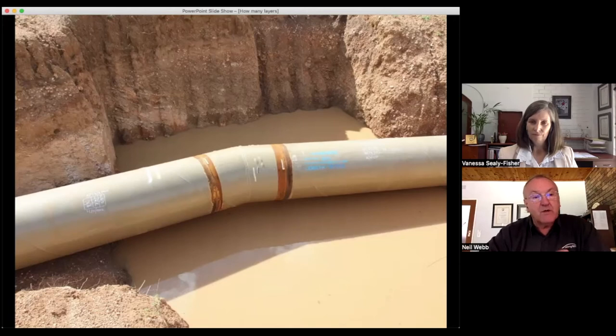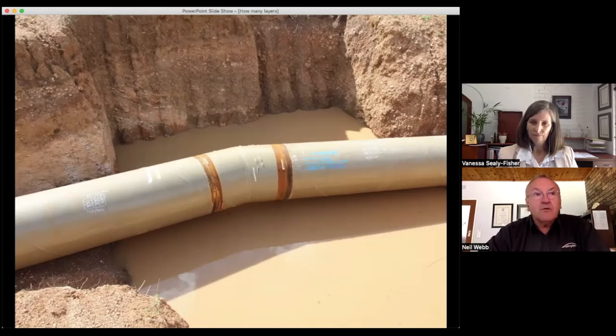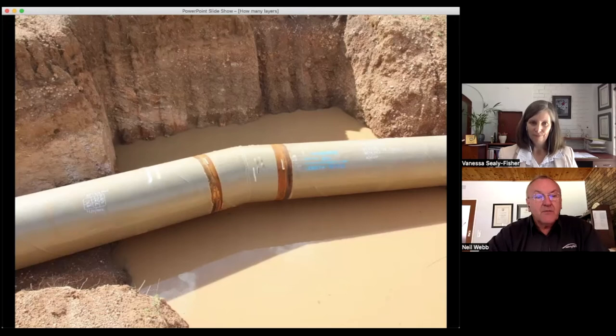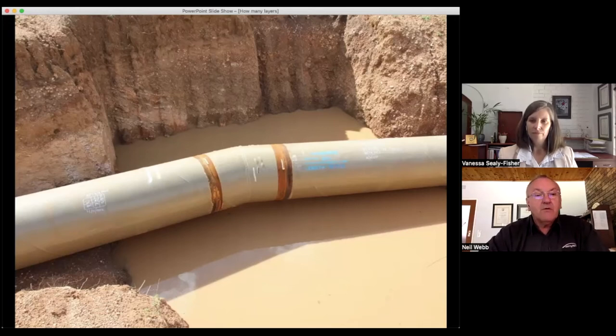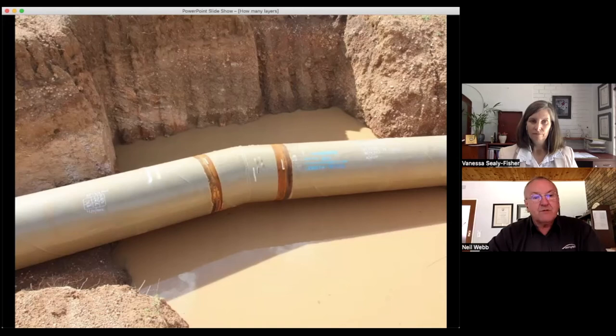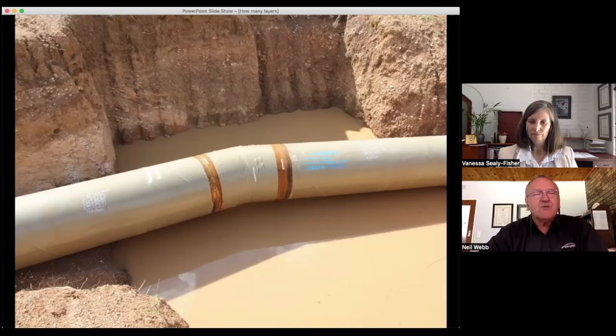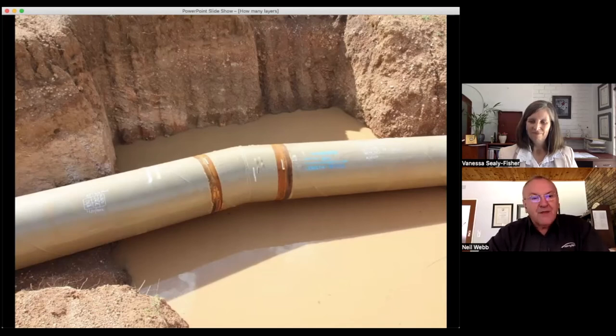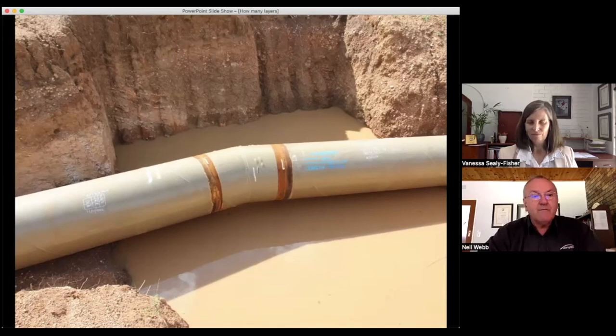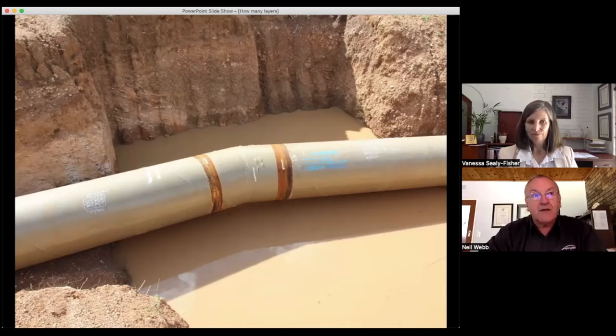This particular problem is due to the spray technique used. Those two components have very different viscosities. If you trigger or release a spray gun during application, you will inevitably get an isocyanate-rich spot, which is a future defect—a latent defect you cannot see.